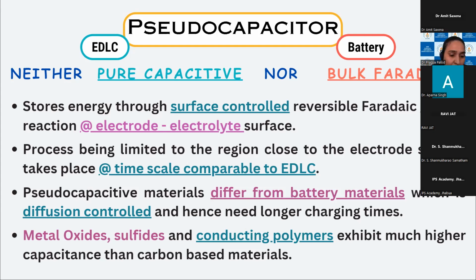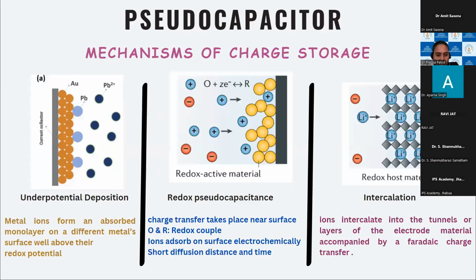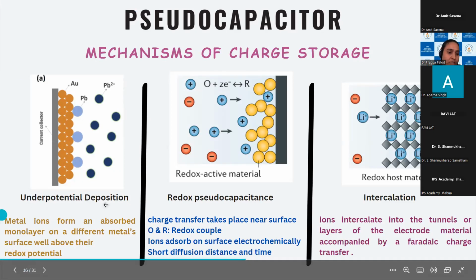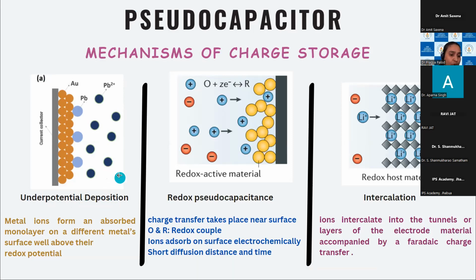Now the preferred materials which exhibit much higher capacitance than carbon based materials are basically transition metal oxides, sulfides, and conducting polymers. Now we quickly have a look at the charge storage mechanism of pseudo capacitor. First one is the underpotential deposition, in which the metal ions from the electrolyte form an adsorbed monolayer on the surface of a different metal whose redox potential is higher than the redox potential of these ions. Now basically the interaction between Pb and gold is much favored in comparison to gold and gold. That's how the adsorption takes place.